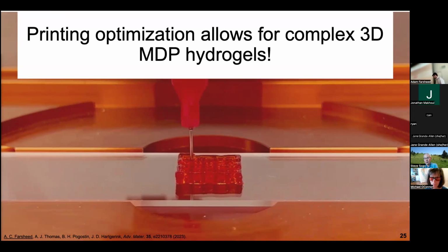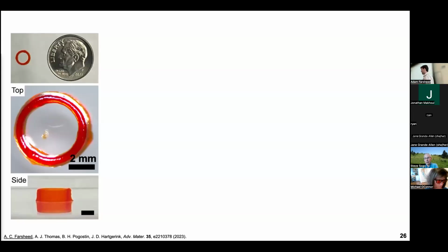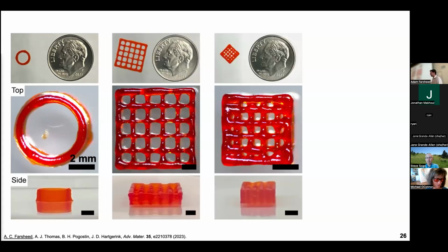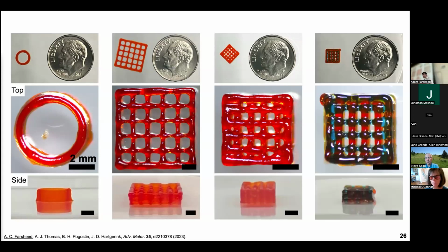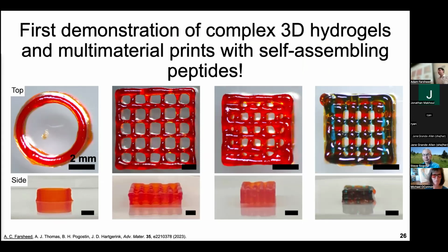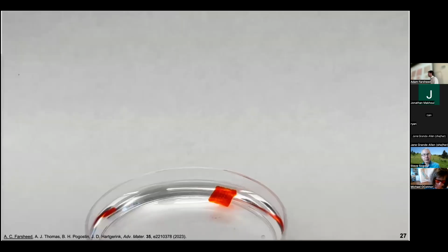But to kind of show some other designs that we went after, we started with the cylinder. And to orient you again, a cylinder was the most complex structure that had ever been printed with a self-assembling peptide. Well, we're able to print a cylinder, and then again, we're able to do a 2x2 and a 1 log pile that were each 10 layers tall. And even more so, we were able to then mix in, so I should have mentioned this earlier, but the orange dye is just a dye that we add to our material to kind of identify it, and that's our K2 material. But the blue dye here in this far right print is our E2 material. And so what we're able to show is we can start to create multi-material prints, which again is the first demonstration that this has been done with a self-assembling peptide system.